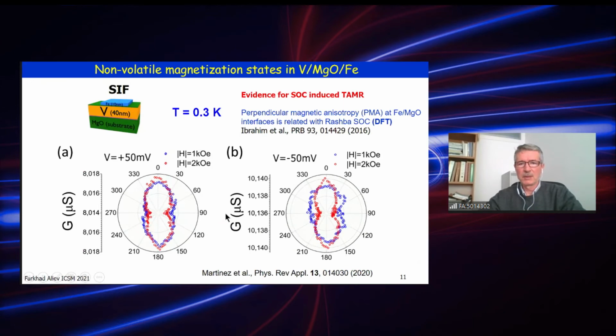The presence of spin-orbit coupling can be tracked also by studying out-of-plane, above-gap conductance anisotropy. This was done in this publication, so we tracked the presence of spin-orbit coupling, but this is also a well-known effect from DFT calculations: perpendicular magnetic anisotropy in iron MgO structures is due to Rashba spin-orbit coupling, and this effect is used in all your computers, because this is standard in magnetic tunnel junction sensors of hard disks.